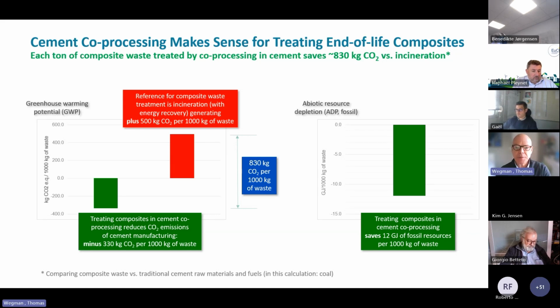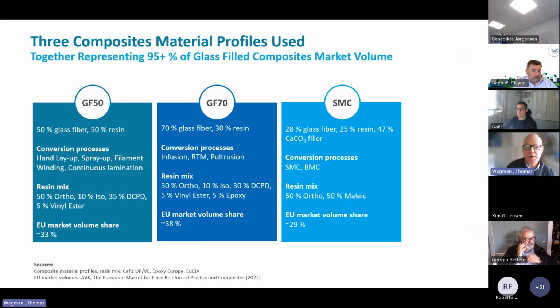The numbers that you see here have been based on different material profiles. We thought that for doing this calculation, it makes sense to look at different material systems that are being used in the composites industry. This is obviously not 100% covering everything, and there are obviously some variations in compositions that you or your customers may use. But we try to separate between a material typical for hand layup and spray up, 50-50 glass fiber and resin, a material used in infusion and pultrusion, more 70-30 glass fiber and resin, and a material typical for SMC, glass fiber and resin both in the 20 to 30% range, and a fair amount of calcium carbonate filler.